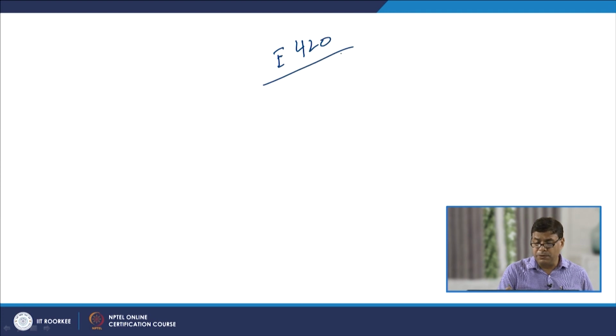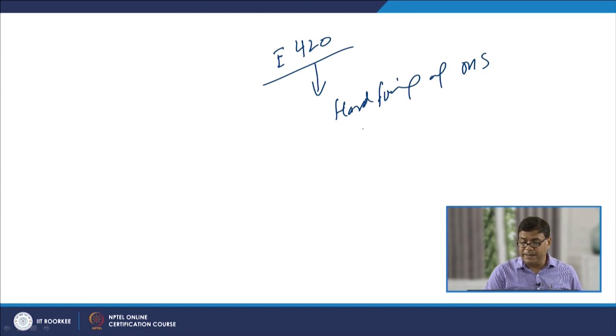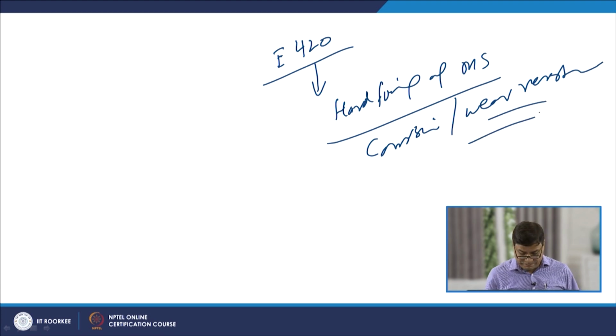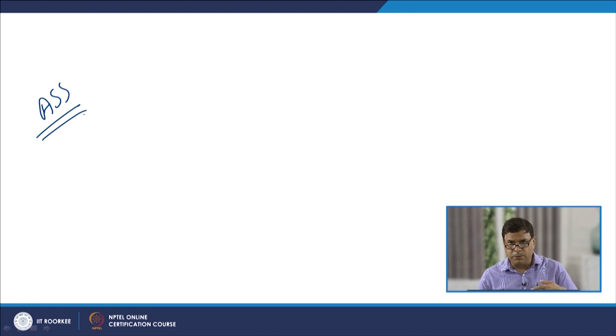At the same time, the electrode E420 is also used for hard facing of simple mild steels, where good corrosion as well as wear resistance is required. So, these are some of the fillers which are used for joining. When we use austenitic stainless steel fillers, as I have said, they help in improving the weldability of the martensitic stainless steel because they offer lower yield strength, greater ductility, greater toughness, and also act as a sink for hydrogen. So, it reduces the cold cracking tendency.